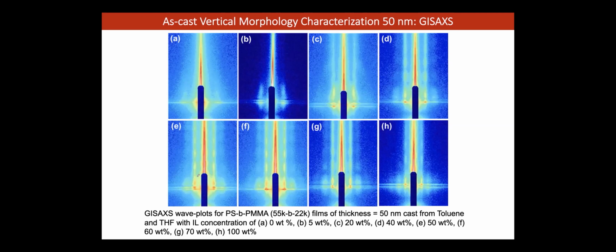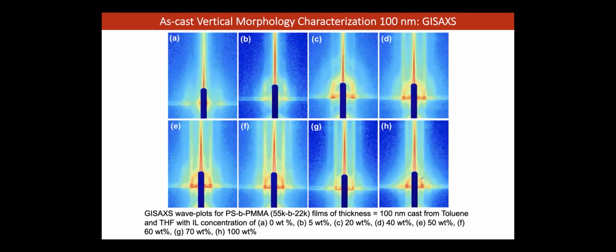So there is still a lot of need for TEM and real space imaging, but at a quick glance, GISAXS gives you great information. And by the time you get to H, you're not in the optimum vertical orientation because the peaks go down. So this is just an illustration. We take all these snapshots. That was a 50 nanometer film for a membrane. And here's an example of the same scenario, but with a 100 nanometer thick film.